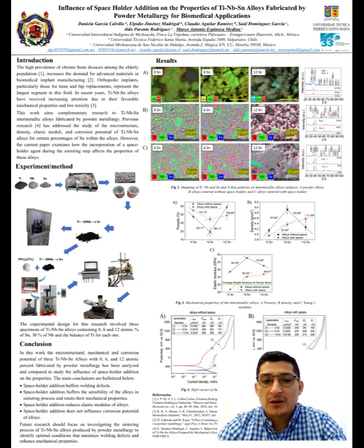The corrosion potential of alloys exhibits similar values. However, the most notable difference lies in the variability of the potential and corrosion current density among samples with different tin percentages in specimens without the space holder. This phenomenon can be attributed to the compactability of the alloys.